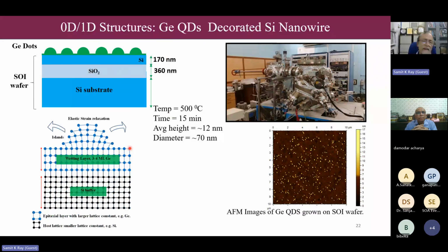Just like a building, if a building is not well designed, there will be stress in the building, exactly the same way. So beyond some critical thickness, the strain will relax and they will give rise to nanoclusters, which you also call quantum dots. So if I can control the technology, I can have germanium quantum dots of a given size. And this is also clear from this atomic force microscopy image. So we can easily get a quantum dot whose diameter is about 70 nanometer. Average height of this quantum dot is about 12 nanometer, and it can be brought down to below about 10 nanometer or so.